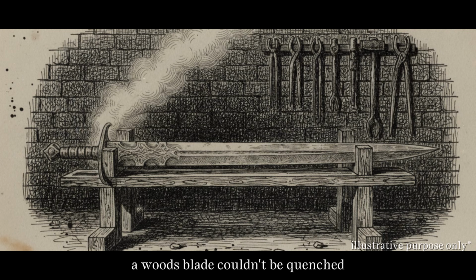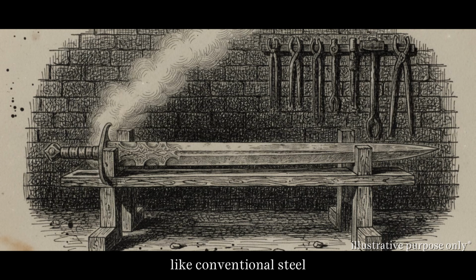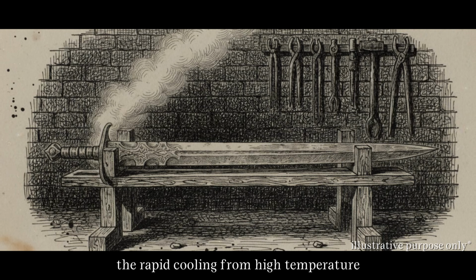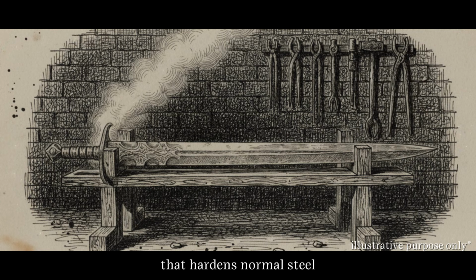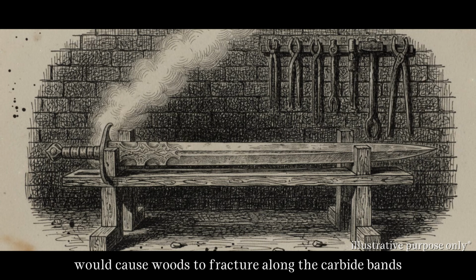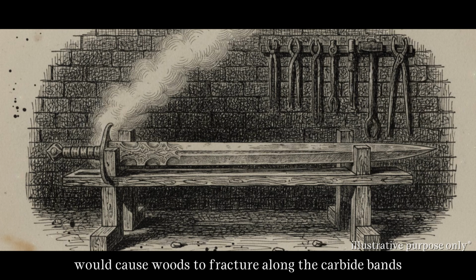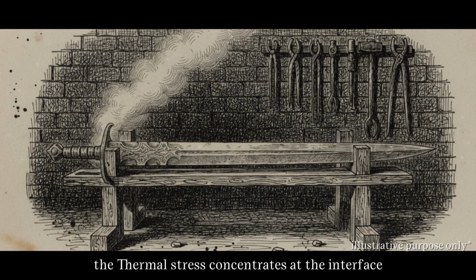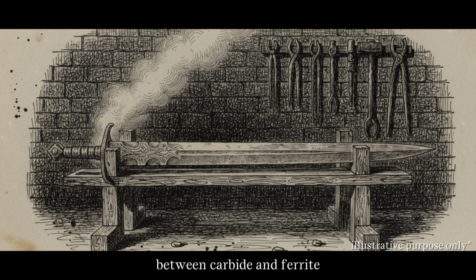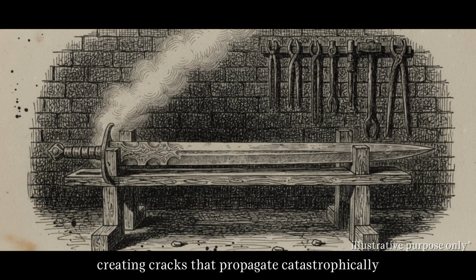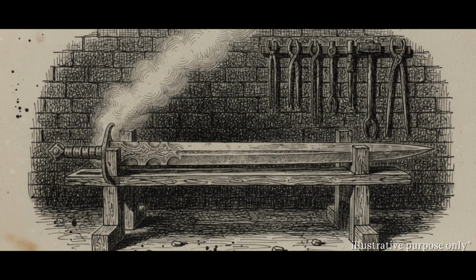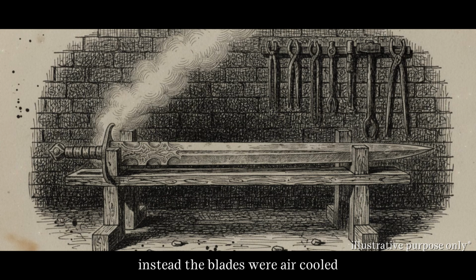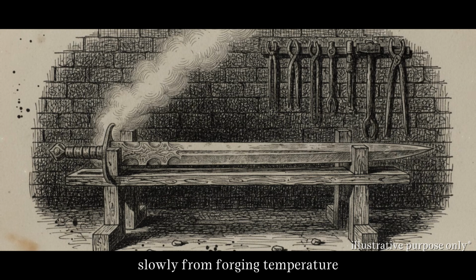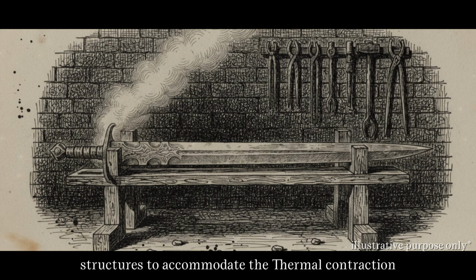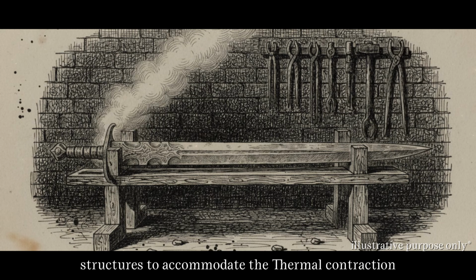A wootz blade couldn't be quenched like conventional steel. The rapid cooling from high temperature that hardens normal steel would cause wootz to fracture along the carbide bands. The thermal stress concentrates at the interface between carbide and ferrite, creating cracks that propagate catastrophically. Instead, the blades were air-cooled slowly from forging temperature. This allowed the carbide structures to accommodate the thermal contraction gradually.